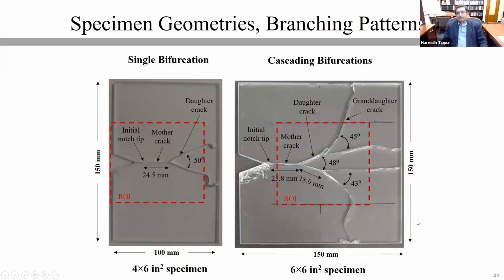Here is the slide showing the branched cracks themselves. You saw a lot of details associated with the image on the left-hand side. The cascading crack bifurcations are shown on the right-hand side. As you see, the original notch tip is here. The region of interest is highlighted by that red line. The mother crack propagated, branched and produced 2 daughter cracks, and then 4 granddaughter cracks eventually. I have also noted some angles over here, although I have no clear explanation as to how to address them due to our limited experimental detail available to us in terms of the lack of T-stress at this stage.